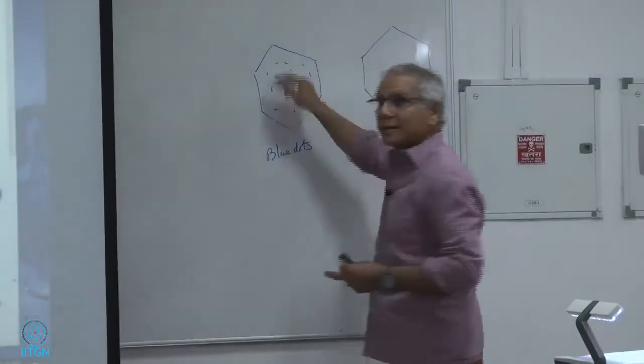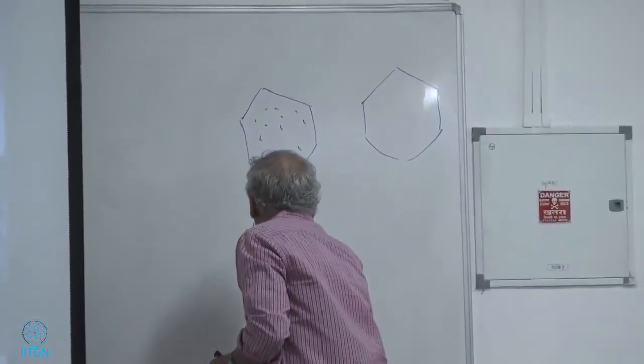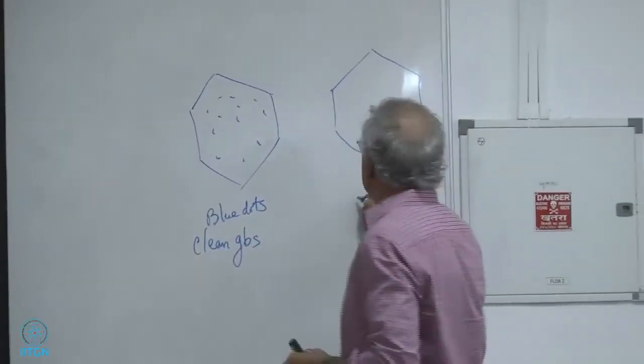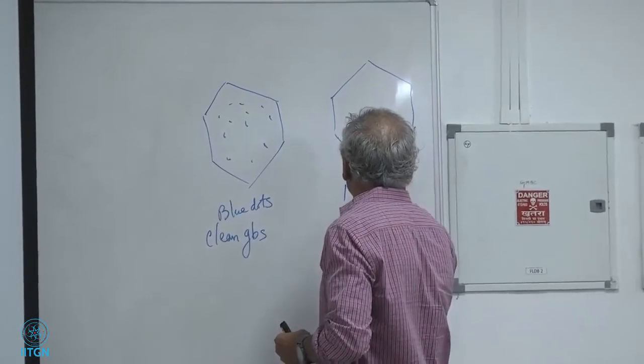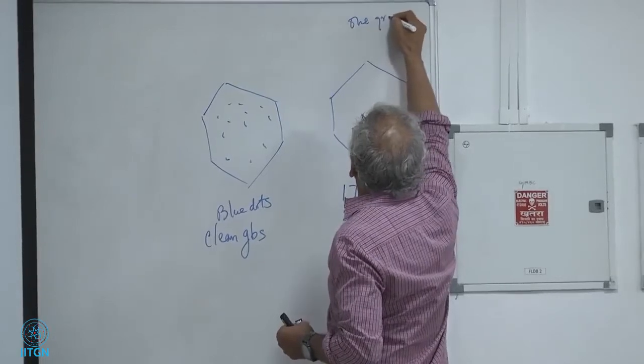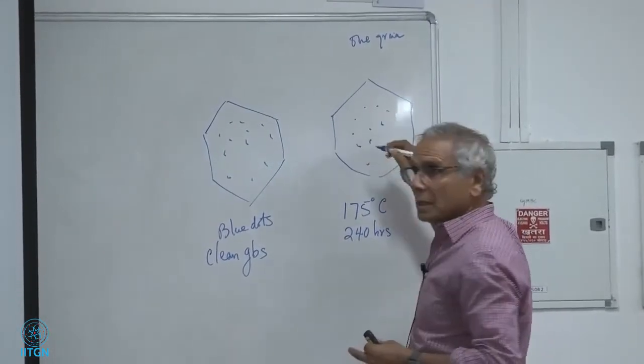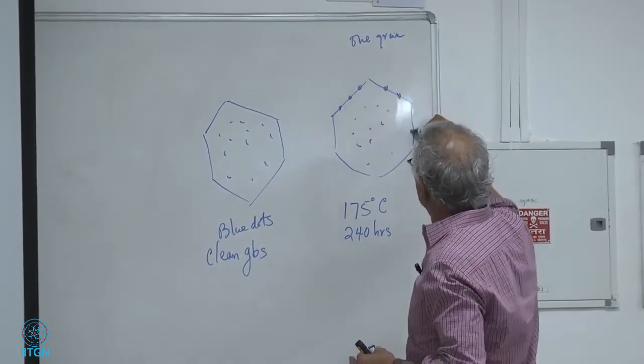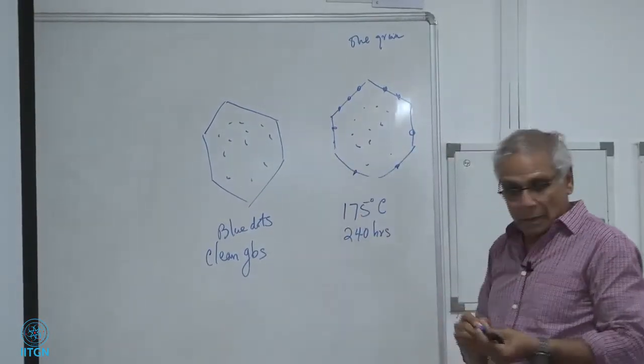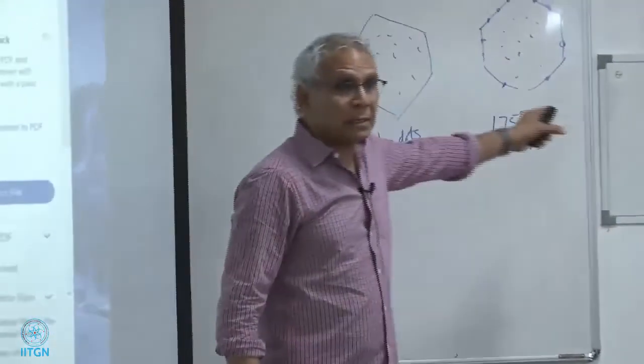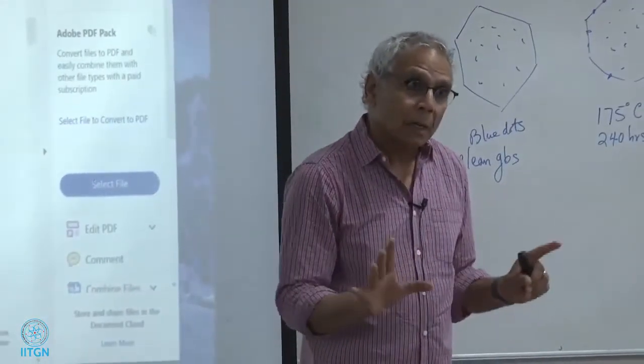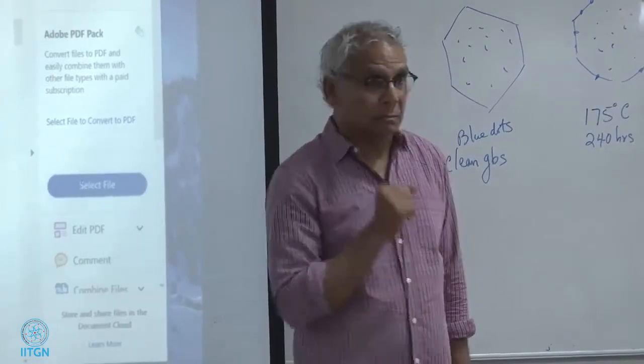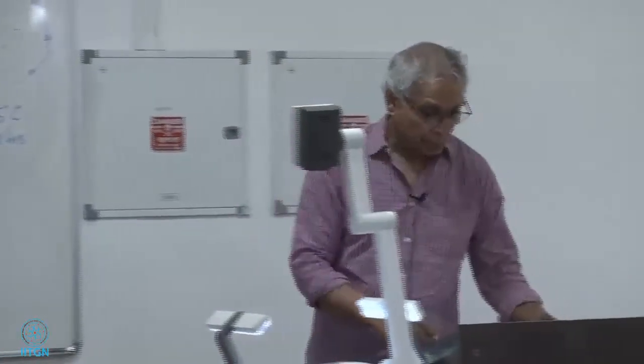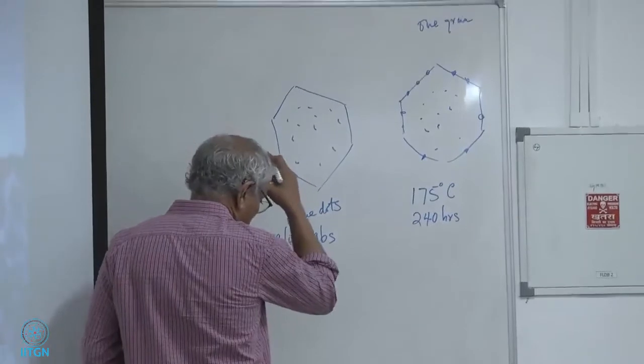So this is as received, the blue dots. Nothing along the grain boundary, clean grain boundaries. This is 175 degrees Celsius, 240 hours. I'm just putting one grain here, just to show what's going on. You still have some precipitates, but now you also have these precipitates. These precipitates will be permanent. Even if the temperature comes down, they will be there. They will be down there.